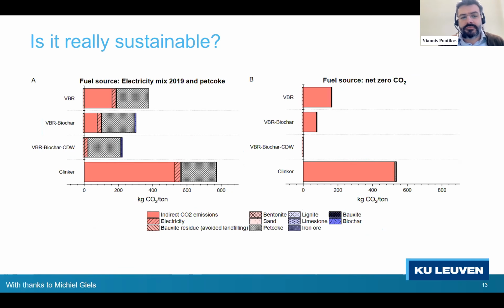Question: is it really sustainable? And my answer is yes, and the extent depends. You see here the clinker, and you see here the VBR, the vitrified bauxite residue. Depending on how you do the reduction, and depending on your energy mix, your electricity mix, you have different numbers. What is important is this one: theoretically that can be 0, because we're not having limestone in the formulation, and we're using electric furnaces to do the job. So if the power really comes from a green source, then indeed that is a precursor that does not have any CO2 emitted.